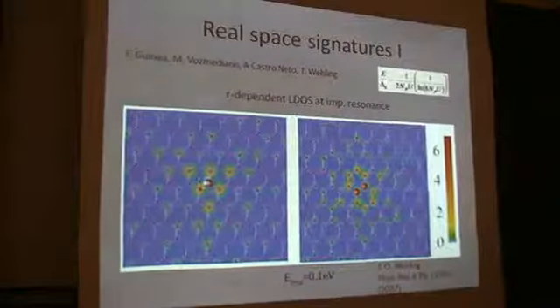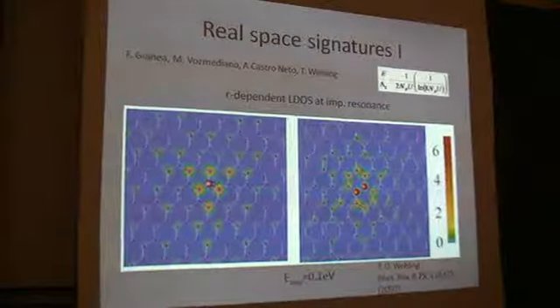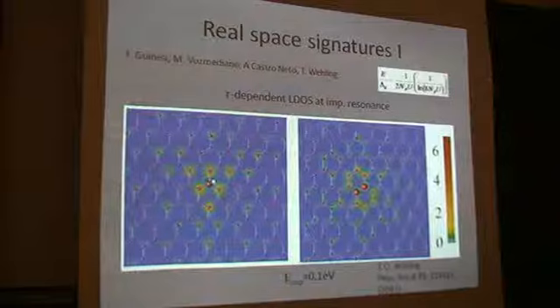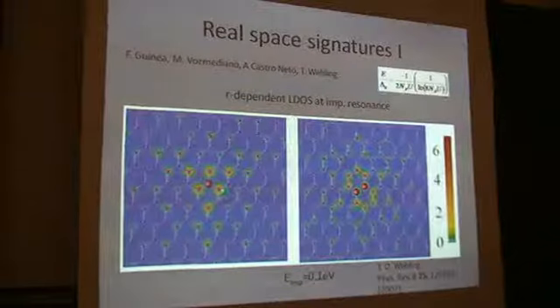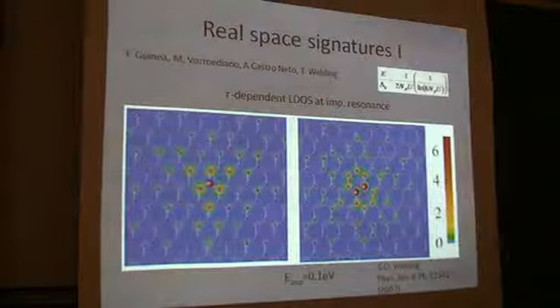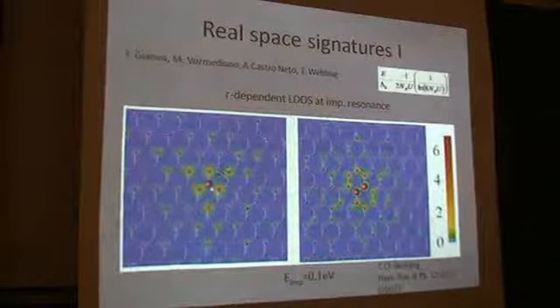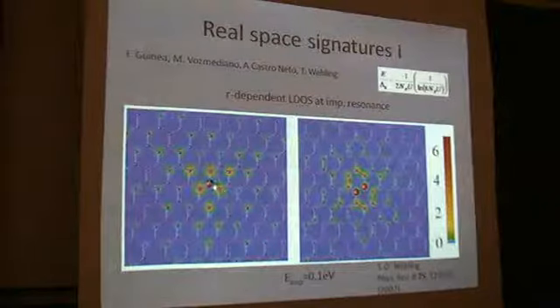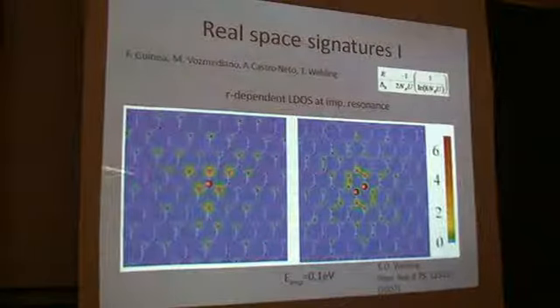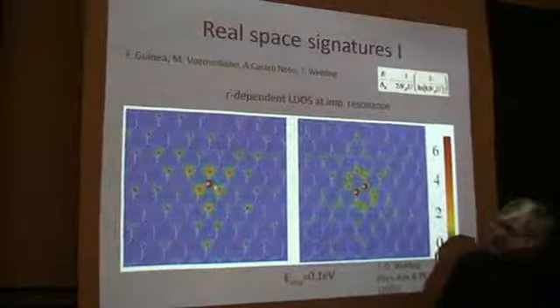So on the impurity site itself, there is very little intensity. Say this is the A sublattice site of graphene. But you can see that actually there is a low energy state at about 0.1 electron volt for our parameters, which has two features. One, it has this Friedel oscillation, which is fully commensurate with the lattice. So we looked at the half-filled case.